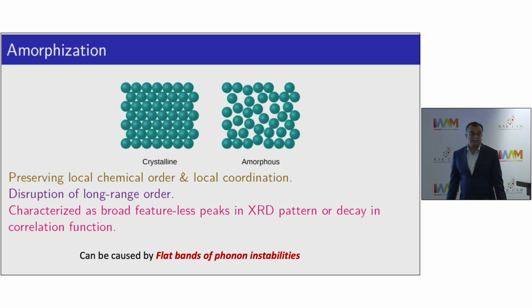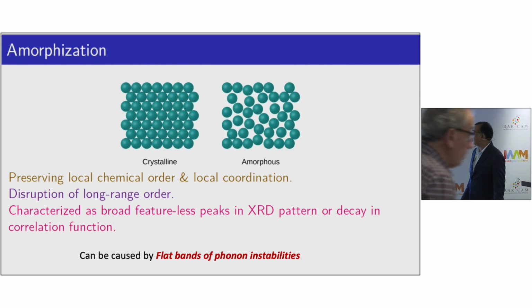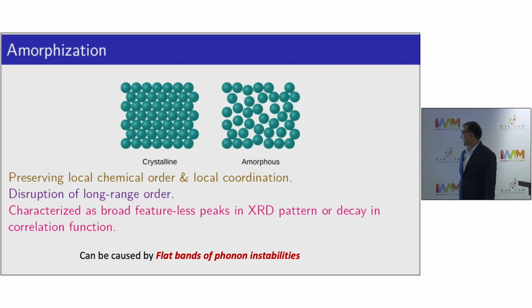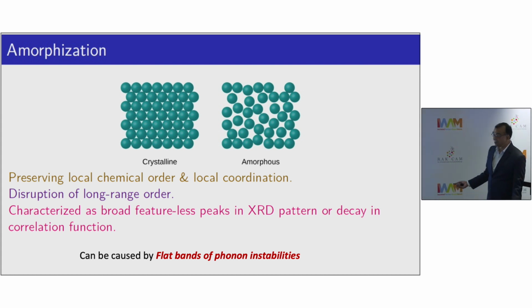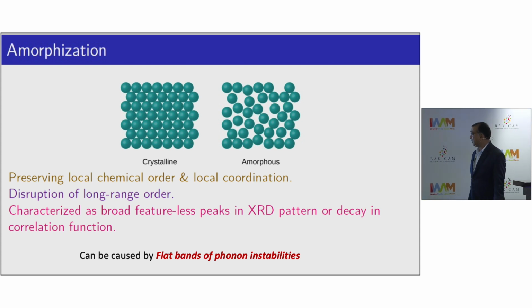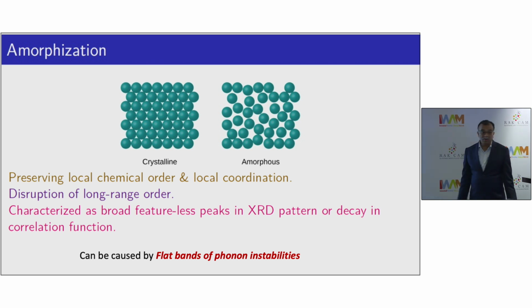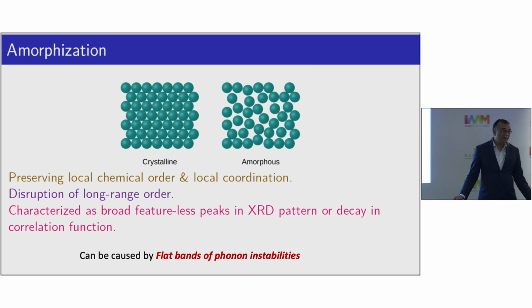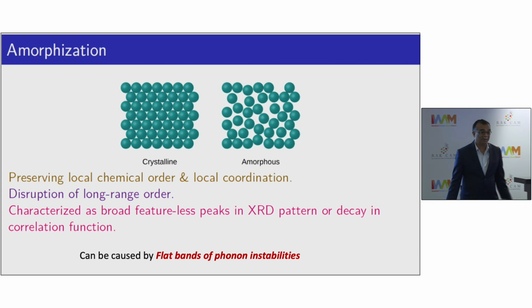And lastly, amorphization, the third aspect of this mechanical response. One goes from a crystalline, perfectly ordered phase to an amorphous, disordered phase, which possibly preserves the local structure and local coordination, but disrupts the long-range ordering in the material completely. And in experiment, you will be able to see this in the X-ray diffraction pattern, where you go from discrete peaks of a crystal to a very broad single peak in the amorphous phase. So what we will show now is this can be caused by a flat band of phonons which are unstable. Okay, that's another message you will get from this talk.